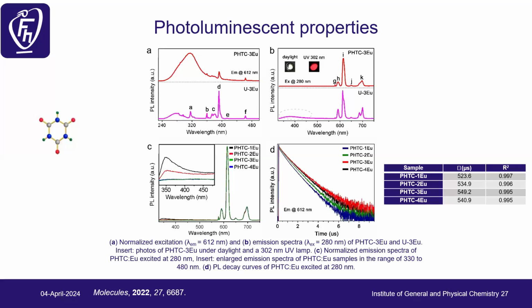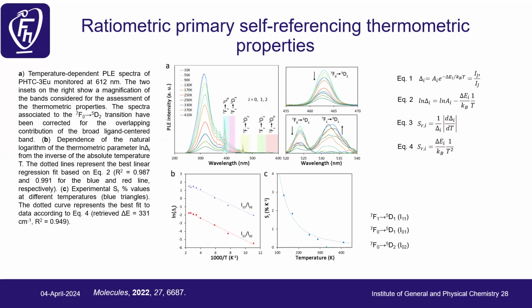Then here was done the doping concentration of the lanthanide, and at the end we found that the 3 percent one is the best concentration. And last time I showed the emission. Here we use the excitation or absorbance to calculate the thermometric properties. So this is also one way, another way how we can use these small lines. Unfortunately, due to the high absorption of the ligand and linker, we need to play a little bit with it, but we can see two different levels in this case. Not the emitting levels, but accepting levels 7F0 and 7F1 are changing with the change of the temperature.